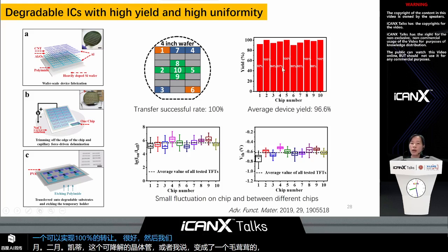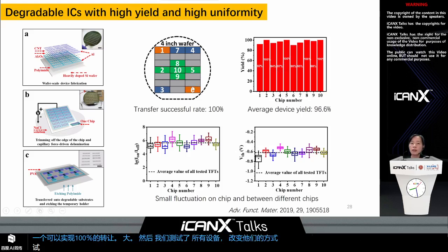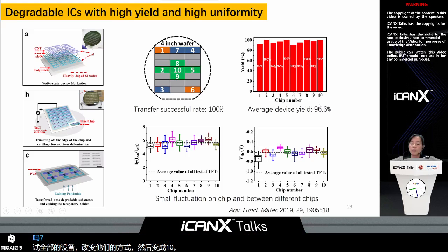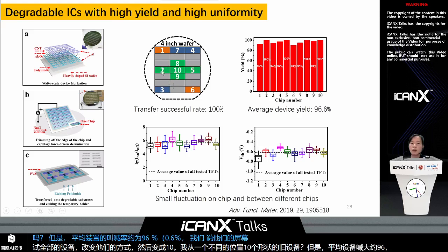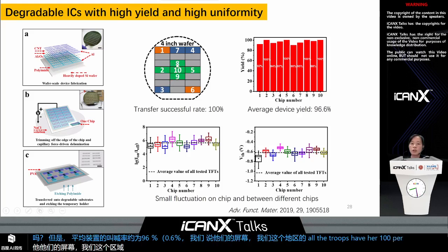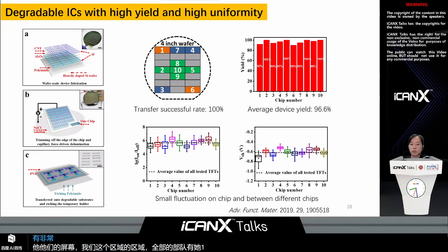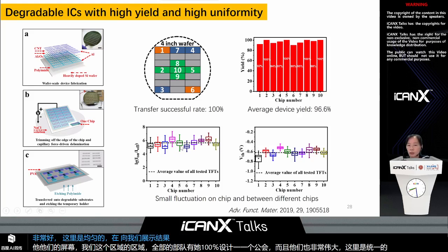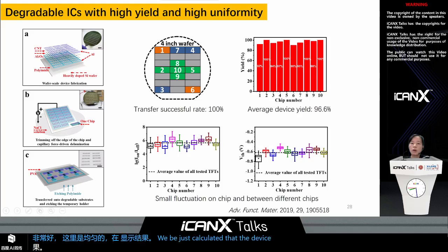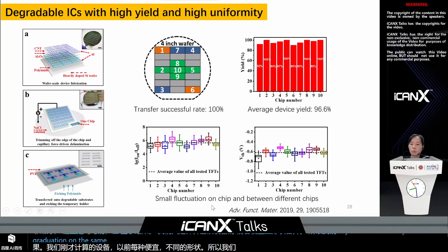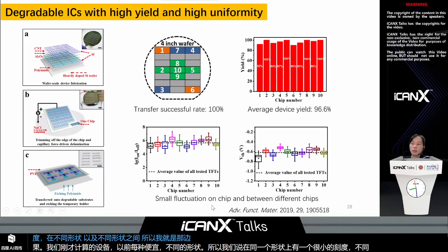And then we tested the devices transferred from the wafer, and we took 10 chips from different locations, and all the devices have an average device yield of about 96.6%. And we see that in this green region, all the chips have a 100% device yield. And they also have very great uniformity. Here we show the result. We just calculated the devices from every chip and among different chips. So we see that there's very small fluctuation on the same chip and also between different chips. That means the uniformity is very good, not only on one chip, but also among different chips.